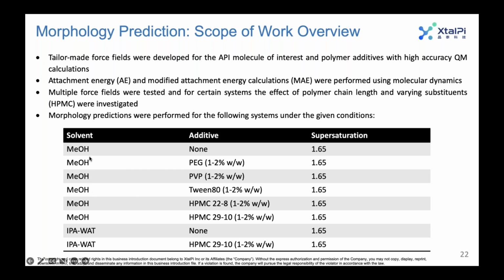So we looked at six simulations performed in MEOH and 2 performed in an IPA water mixture. 2 of the simulations did not incorporate additives, and the rest of them had different additives in them. And we used a supersaturation of 1.65 for all of these simulations.